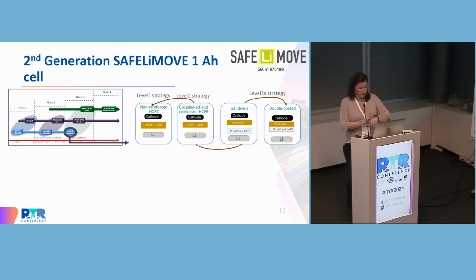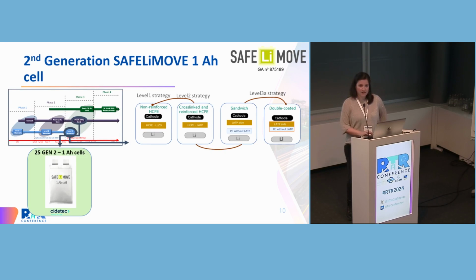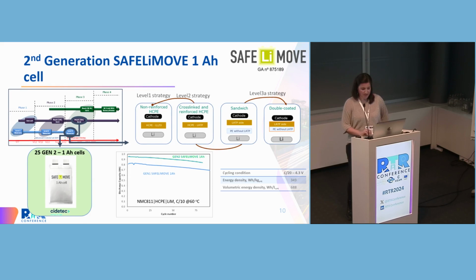Nevertheless, there was still a lot to do, and this took us to the last part of the development at material level. So this is the case of the level 3 materials, where we developed a double-layer electrolyte, where we wanted to have a LATP-rich layer in contact with the cathode to improve the electrochemical stability, and a soft interlayer in contact with the lithium metal, that was a polymer-rich layer. So these materials were used to develop the second generation 1 ampere hour cells.